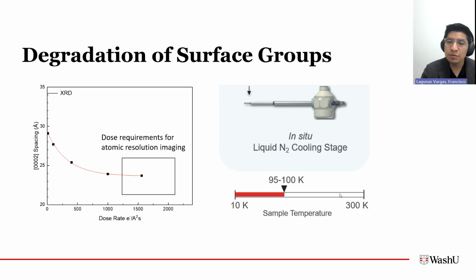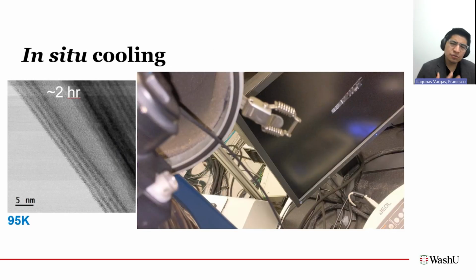So I mentioned some of the tools that we have as microscopists is changing the local environment of the sample. A common approach for looking at organic materials is to use cryogenic STEM, where you take your sample, put it in one of these TEM holders that has a liquid nitrogen tank, and cool it down to about 100 Kelvin. And at these low temperatures, the material should be a lot more stable under the electron beam. The challenge with this is that you're cooling a big metal rod from room temperature down to 100 Kelvin, and the rod itself will compress, and you'll see a lot of thermal drift in your imaging.